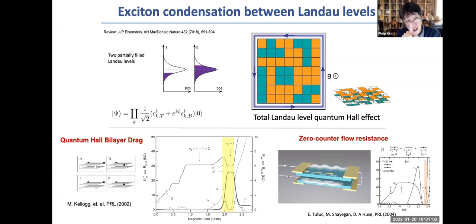If you connect the top layer and the bottom layer in such a way that the current flowing in one layer goes against the current in the other layer, this is the so-called counterflow geometry. If indeed excitons form here, and if they condense, the exciton itself is a superfluidic state and can flow without any dissipation. Now, if the exciton flows, the electron moves one way, and the hole moves the same way, which means the currents are moving in opposite directions. If we flow the current in the counterflow geometry, you expect to see no dissipation. It's almost like a superconducting state. And indeed, this has also been beautifully demonstrated in the quantum Hall bilayer.